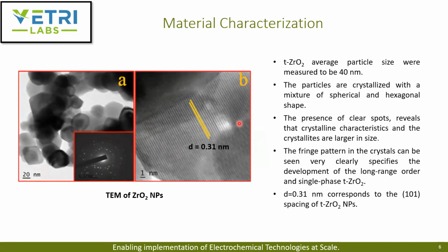Then they did the TEM analysis to confirm the particle size, and they found it to be around 40 nanometers, which corresponds with their XRD calculated particle size. And the particles were crystallized with a mixture of spherical and hexagonal shapes, from their SAED pattern. And when they did the high resolution TEM, they calculated the lattice fringes, and they found it to be 0.31 nanometer, corresponding to the 101 spacing of zirconia oxide nanoparticles.